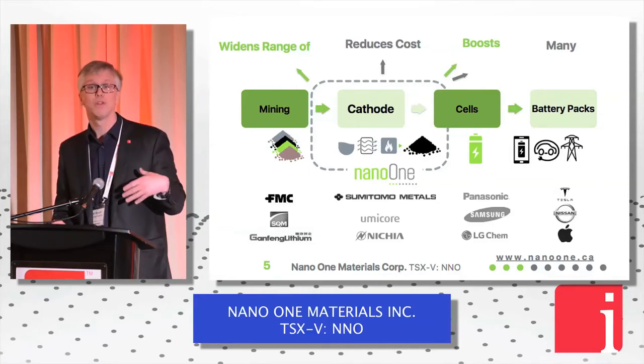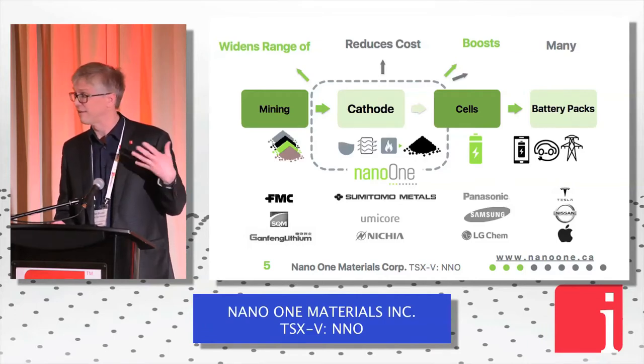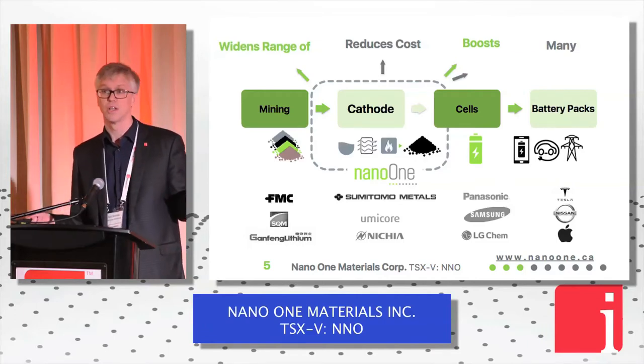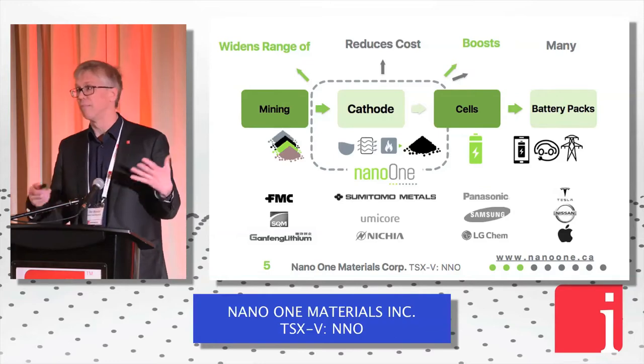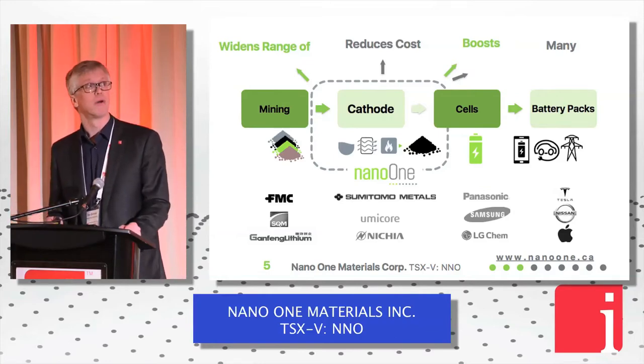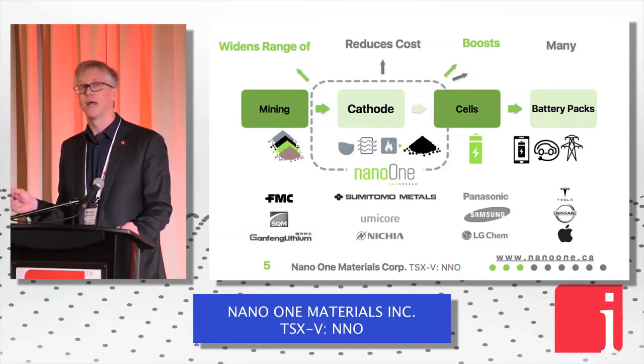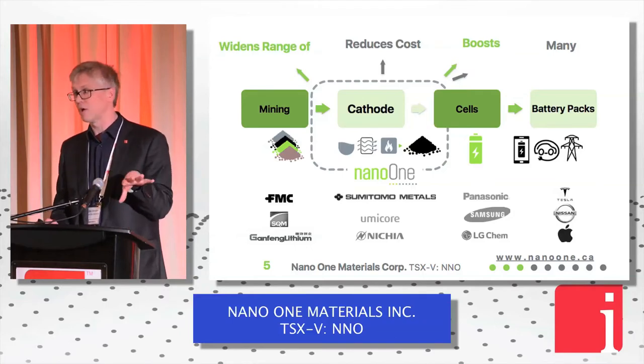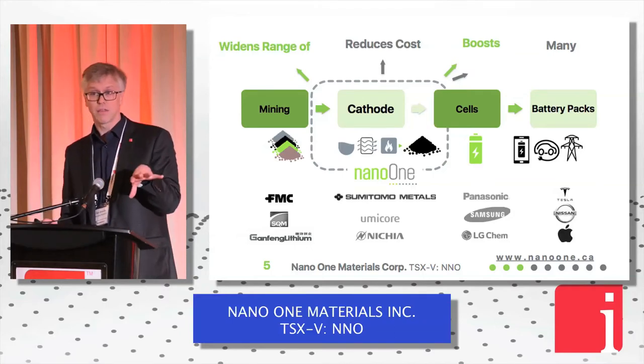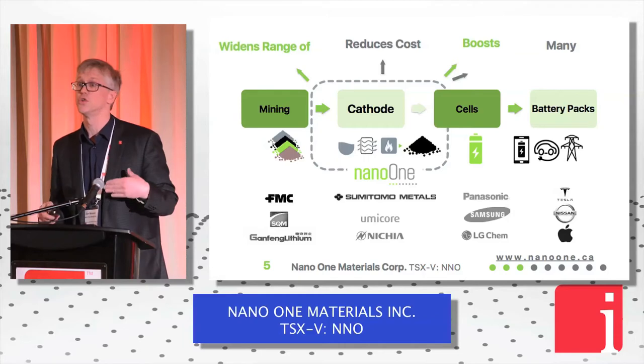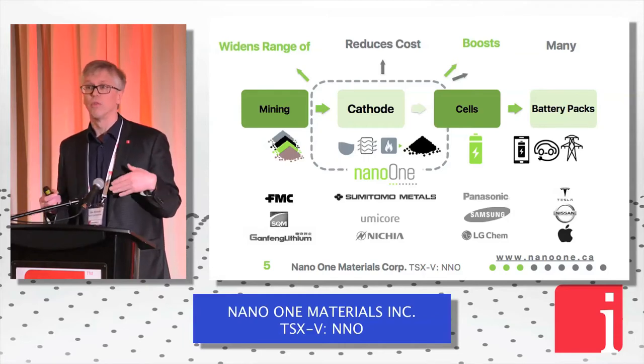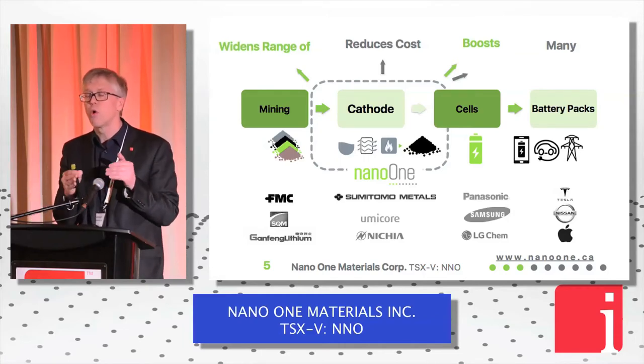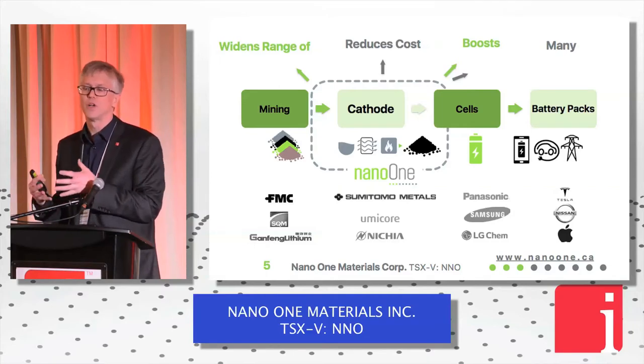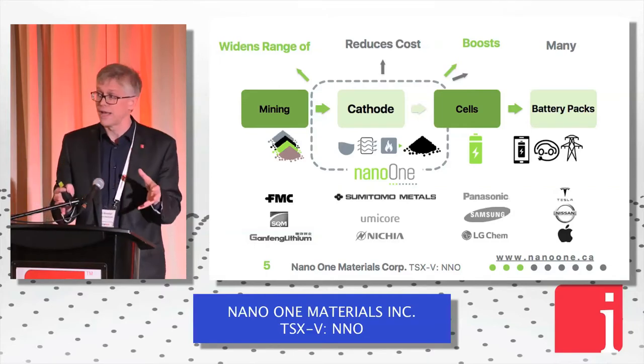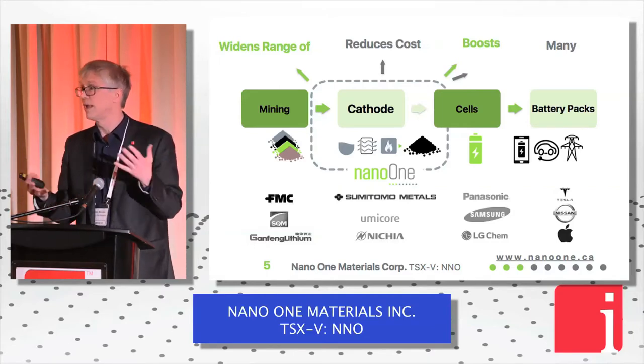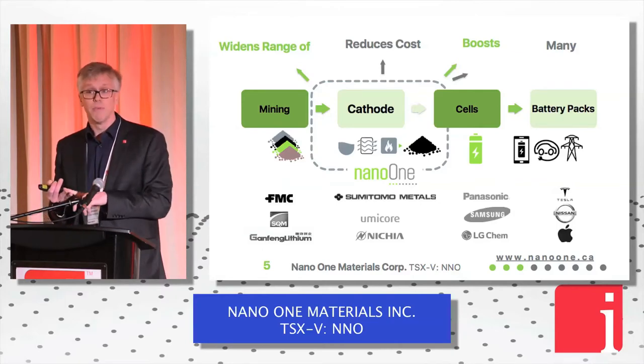Again, it's a chemical assembly process for putting together lithium, nickel, and manganese into structured materials. We're aligning atoms in a bulk manner into these powders. We add value across the supply chain. Our methodology allows cathode companies or battery companies to use a wider grade of lithium. The industry is moving more and more towards what's called lithium hydroxide. We can enable lithium carbonate, a cheaper raw material going into the battery. We don't need to grind or mill the lithium beforehand.